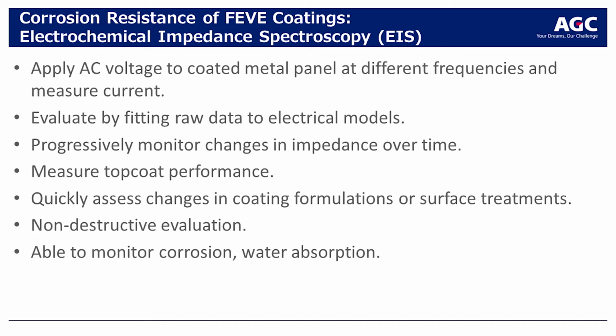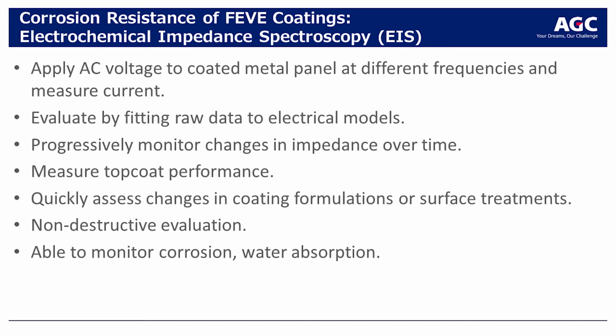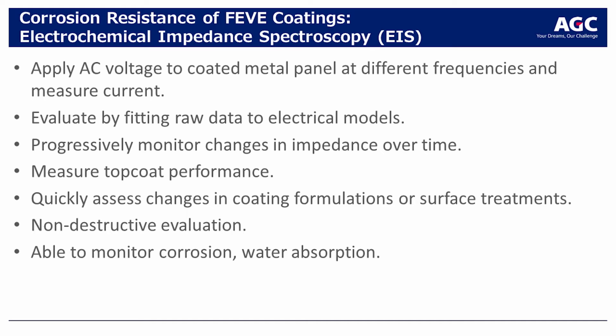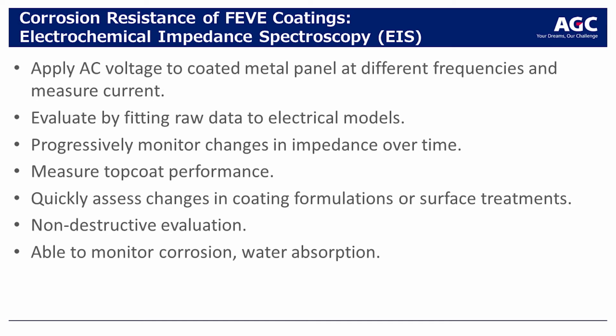What you're doing is applying an AC voltage to a coated metal panel at different frequencies. You're measuring the current. You fit that raw data to various electrical models, and you can progressively monitor the change in impedance over time. What you're hoping for is that the impedance stays very high over the life of the coating. We can measure top coat performance by putting the coating directly onto the metal surface, so now we can measure only how much that top coat is contributing to the corrosion resistance. It allows you to quickly assess changes in coating formulations or surface treatments.